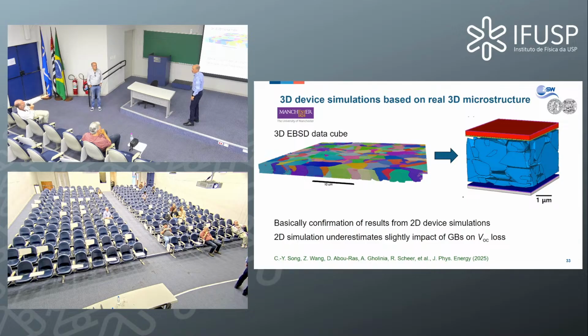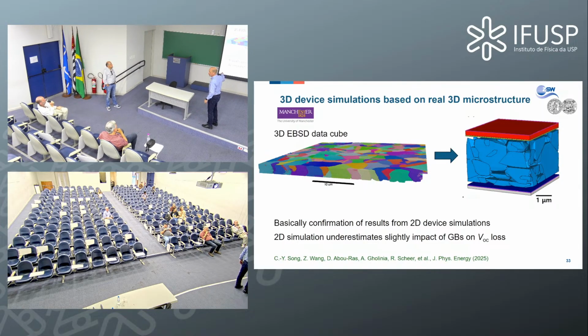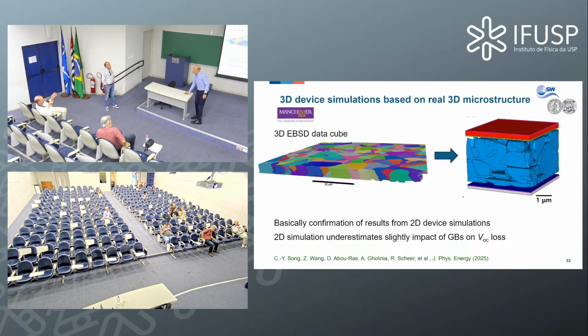What technique did you use to get this left image here? This one here is a 3D EBSD measurement. So it's possible to do it really in 3 dimensions. It's not a trick, not a kind of tomography. Exactly. It's a sequential process where I measure EBSD on a surface, and then I use a FIB instrument, a focused ion beam machine, to slice a very thin slice of 50 nanometers away, and then I acquire another EBSD map. And then another slice, another, and so on, and the stack can be reconstructed to result in a 3-dimensional data cube. Okay, great, thank you. But this is established, it's not our invention.